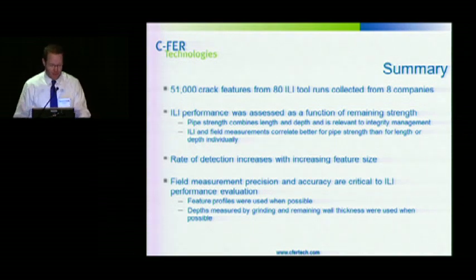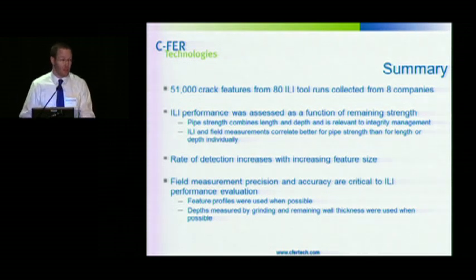Here's a summary of the project. We collected roughly 51,000 crack features from 80 different ILI tool runs from 8 different companies. ILI performance was assessed as a function of remaining strength. Okay, this was a choice that we made. It didn't have to be done this way.